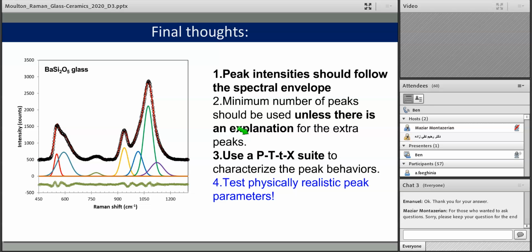I'm going to speed through here. Just some final thoughts on curve fitting. Your overall peaks should follow the envelope, and we saw a bad fit is where the peaks don't follow the envelope. Try to use the minimum peaks as necessary. And if you can, use some suite of samples that's changing the same peaks with pressure, temperature, time, or composition, or some other reaction, so that you can follow the peaks.